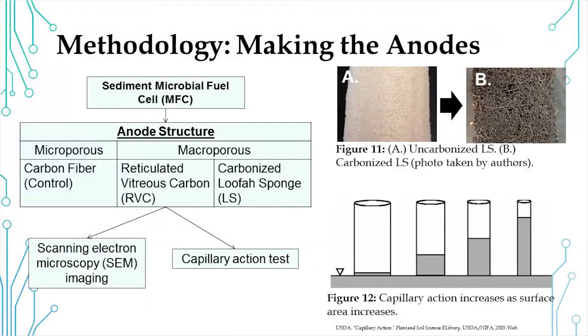Based on the works of Logan, Yuan, and Zhao, we hypothesized that macroporous structures and nanostructured surface coatings will increase the overall MFC performance by improving the bacterial adhesion and extracellular electron transfer. All research was conducted in our high school lab. We engineered 9 different anode designs, focusing on the variations of base structure and surface coating. A carbonized loofah sponge was used as a cheaper alternative to commercial RVC in Figure 11. Carbon fiber acted as a control.